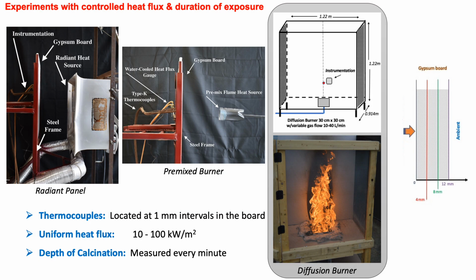So we performed a series of experiments with controlled heat flux and duration of exposure. We started with a radiant panel, and so on the left photo, there is a radiant heat source. That panel was exposed to a 2 foot by 2 foot section of drywall. In the drywall, we mounted Type K thermocouples every millimeter from the surface. So we took the temperature at the surface exposed to the heat side, all the way through the drywall, which is a 1/2 inch drywall, so 12 millimeters. And we went 1 millimeter in depth throughout the board. So we did the radiant panel, and we had various constant heat fluxes and durations from that.